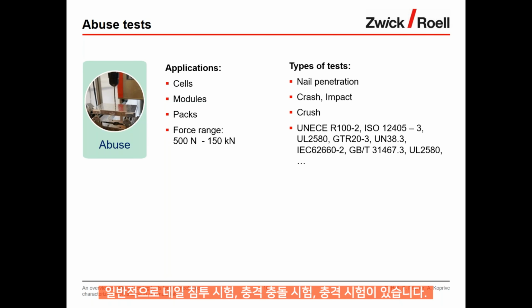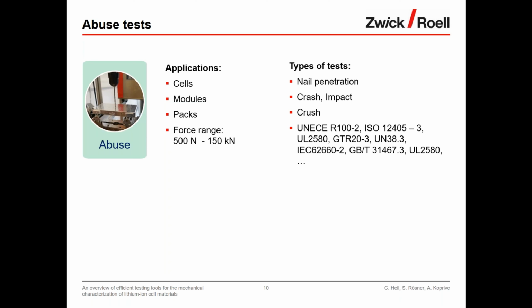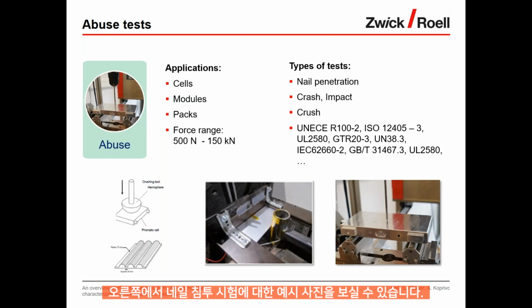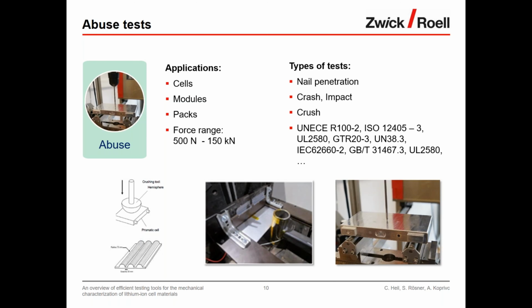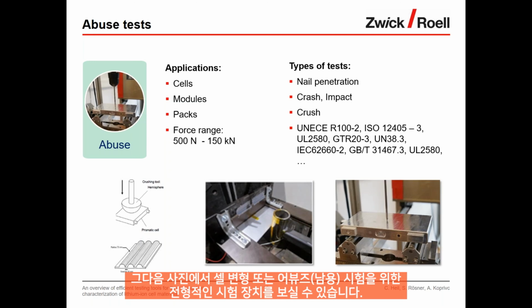So typical tests are nail penetration tests, crash impact tests, crush tests, and the abuse tests are actually the only test area which is highly standardized. The safety tests are well standardized with international organizations, and so that is well documented, well thought through, and you have a good guideline for the testing. Here's some examples. On the right side, you see a nail penetration test, and a crush test in the middle, and some other typical test devices for deforming or abuse testing of a cell.